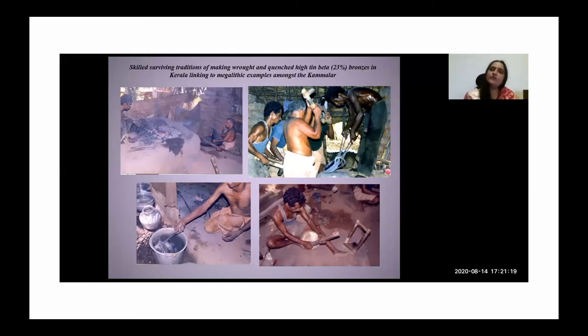Now, why were they also aiming for that? Of course, I was mentioning how the alloy becomes more ductile. So that is one aspect of it. But also, it seems that when you scrape and polish this beta phase, you get this remarkable golden color. It's very brilliant golden. And so perhaps it was used in place of gold in a way. And just below, you're seeing how this artisan is actually working this vessel in this very intricate sort of way.